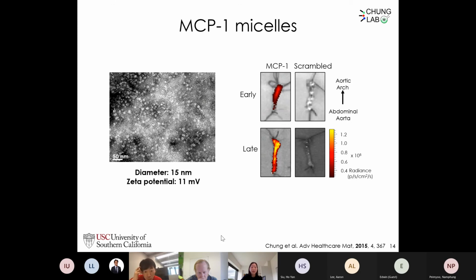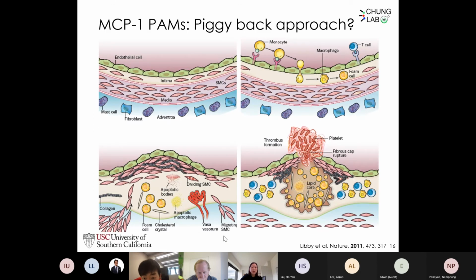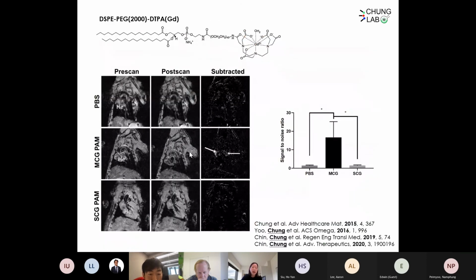of this disease. And then at USC, we added gadolinium components for MRI contrast agents just to get it more clinically relevant. And we're able to show that compared to the scramble, it can pick up on plaque components, as further quantified here. And we also went on to actually add a therapeutic, a collagenase cleavable linker peptide to flood the proteases that are there, to make a theranostic system.